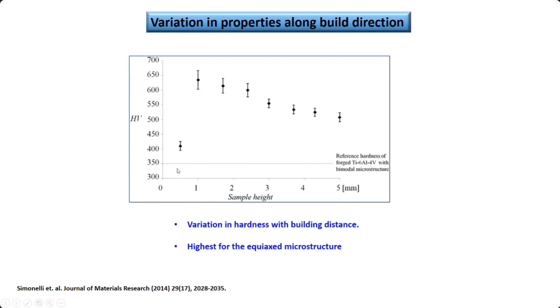This is what it is showing here. The interesting thing is that this is a base material - a reference for the forged, conventionally processed titanium alloy, same alloy - and it has a hardness of only around 350, whereas the additively manufactured component always has hardness at a higher level compared to the base structure. This is again because additive manufacturing is able to produce finer microstructure.